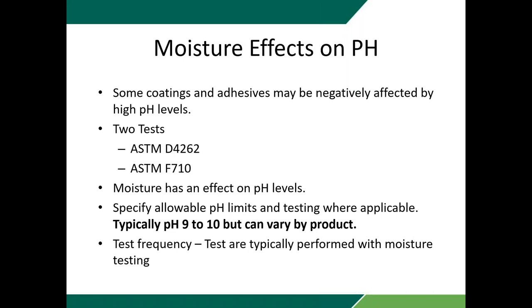But typically pH limits that manufacturers of coatings are going to be looking for are, you know, maximum of 9 to 10, and that's about the lowest you're going to be able to get concrete, really. It's very difficult to get it much lower than a pH of 9. But in that case, you need to be actually looking at the particular product and what their recommendations are for pH.